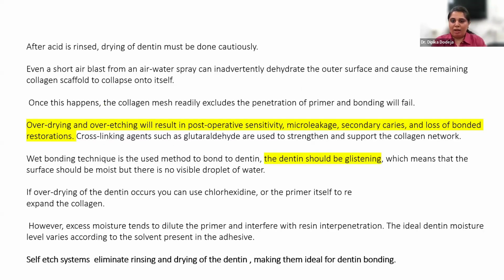Okay. So once you have etched the dentine and you rinse it and then you dry it, now this is the most important step that we should be looking at. Over drying the dentine is what will create all the complications like post-operative sensitivity, micro leakage, secondary caries, etc. How? When you over dry the dentine, the collagen fibers which are exposed will collapse. This collapse of collagen fibers will not let the adhesive in completely and form a hybrid layer.